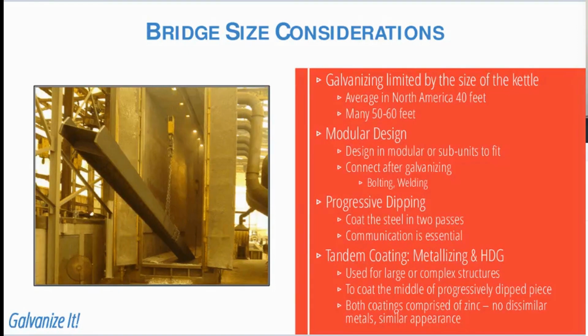But there are many 50 to 60 foot kettles, and depths can range anywhere from 6 to 12 feet and widths from 5 to 8 feet. There are options to galvanize bigger spans, though. You can use modular design and then bolt or weld after galvanizing. You can also look at a process called progressive dip galvanizing. That means if about half the part can fit into the bath, it can be galvanized on one side, rehung, and then dipped on the remaining surface. In essence, this could nearly double the size that could be coated.